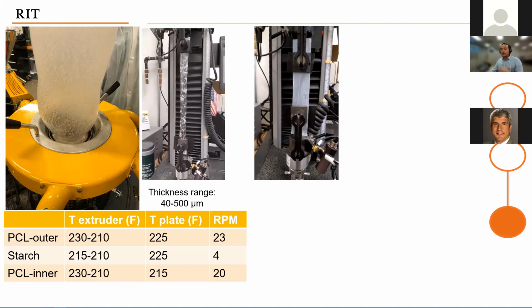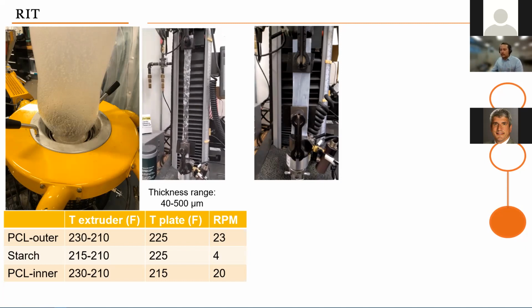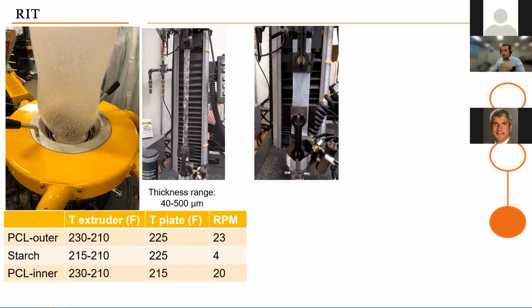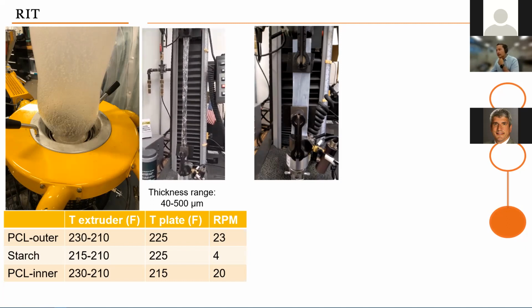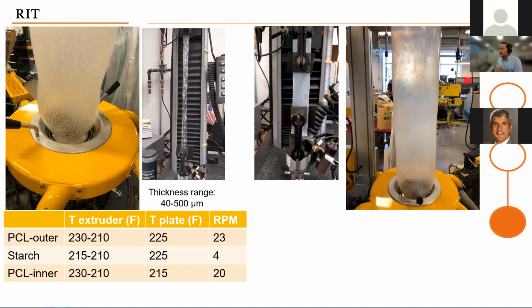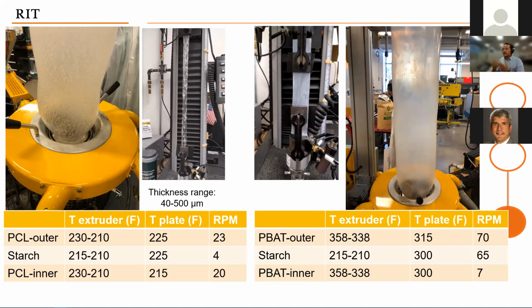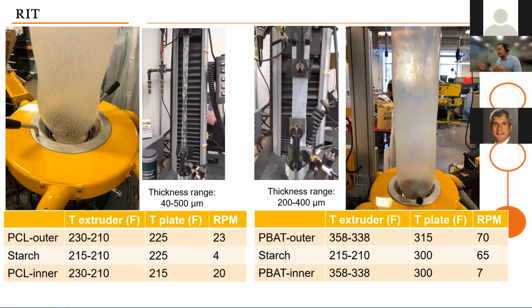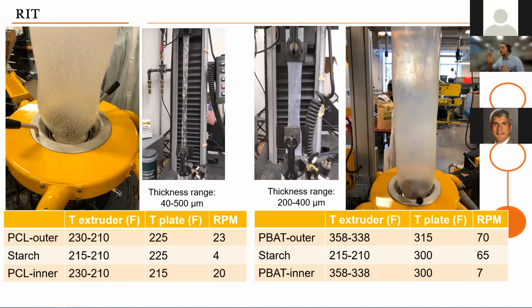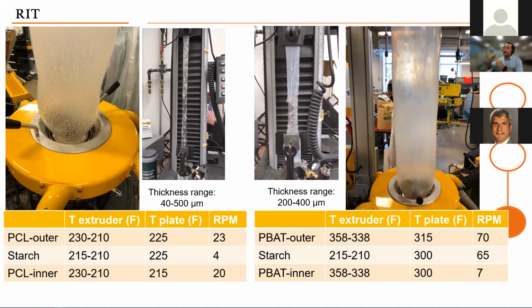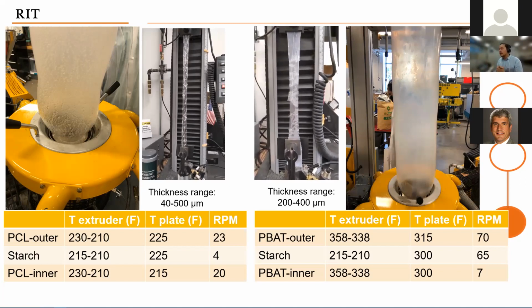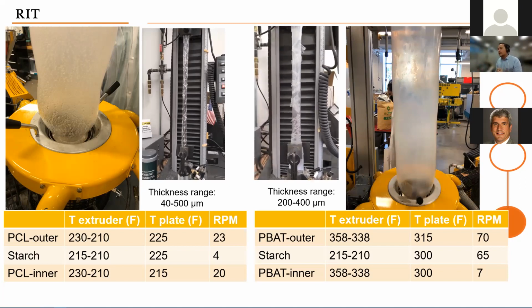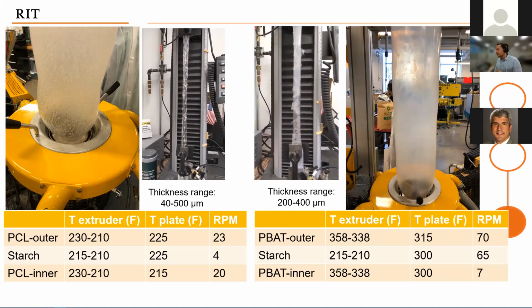Then the second prototype we made was with PBAT. We were a little bit reluctant to use PBAT because the processing temperatures are much higher, like 120 Fahrenheit higher, and we were scared that it was going to burn our starch. But we were able to produce a very homogeneous prototype. And the speeds at which we were inputting starch were much higher. So it was producing a very homogeneous sample that, as you see now in the video, also performs very correctly. The outer layers carry the whole mechanical tension, and the starch flows inside. The thickness range was a little bit bigger than what we expected, but way more homogeneous. So that was great.